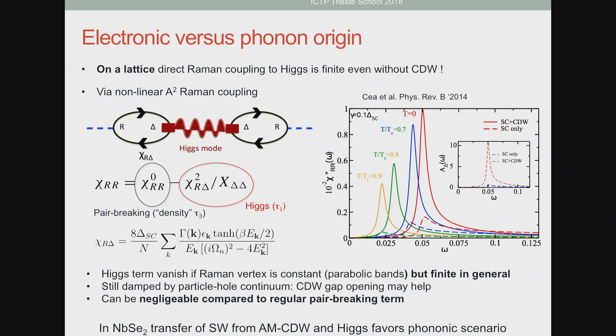So in this picture, it's at 2 delta. Yeah. So the way it becomes more long-lived is because you have a CDW gap. That gaps out part of the Fermi surface, and that gives it a longer lifetime. But it's still at 2 delta. No, for this, you need to have the CDW phase.